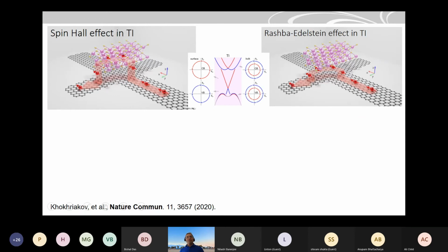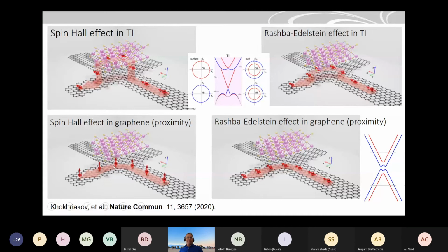So there may be many possibilities, and I can show you some possibilities one by one. We can rule out that it is coming from the TI bulk states, because it is a highly doped topological insulator and we don't expect any gate tunability. We can also rule out the surface states, because we have some interface resistance between graphene and TI, and also the sign is expected not to change if it is only surface states. If it is only TI, the sign should not change because it is just one band like this.